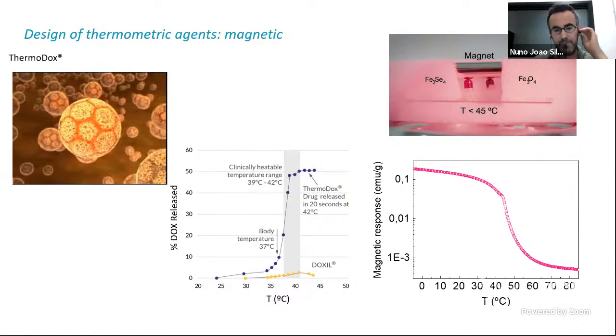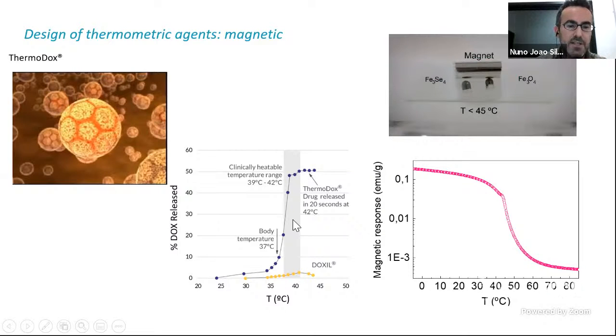So, why can this be interesting? I give you this example, Thermodox. It's a drug that is already on the market, and it's designed to release doxorubicin at a given temperature threshold. So it's designed to keep the drug inside until this temperature is crossed, and then it releases the drug. So you can control where this drug is being released. And now, our point is, you cannot really control in vivo if you don't know the temperature. So if you could have a magnetic particle that gives you a response when you cross this temperature threshold, that would be interesting to control temperature in this relevant application.